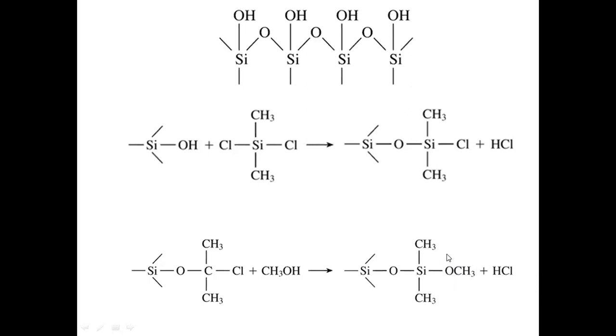So this doesn't have any unwanted physical adsorbable sites such as OH groups, and this stationary phase is very useful for the separation of the solute molecules without initiating the adsorption process. So this chemical treatment of the stationary phase will be done in order to destroy the unwanted physical adsorption process. This will be done by treating the stationary phase with reagents such as dichloro-dimethylsilane or hexamethyldisilazane, followed by washing with either acid or alkali or methanol.